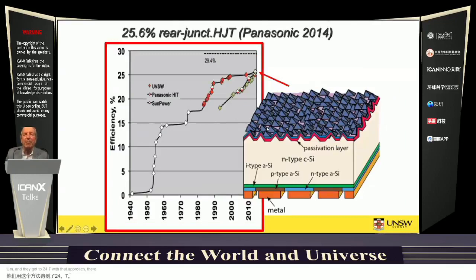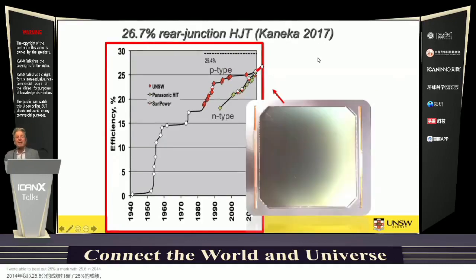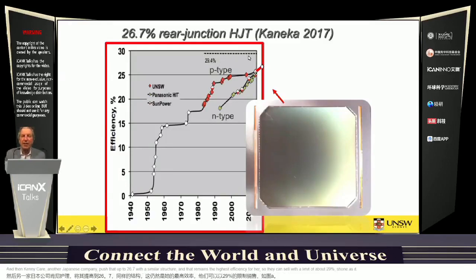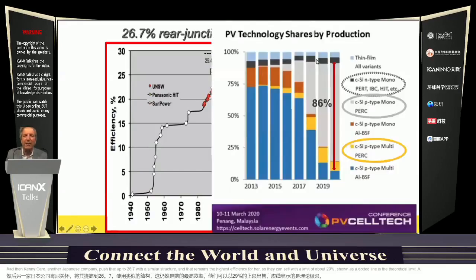And then by combining their approach with the Stanford University rear contact approach, we were able to beat our 25% mark with 25.6 in 2014. And then Kaneka, another Japanese company, pushed that up to 26.7 with a similar structure. And that remains the highest efficiency for a silicon cell, with a limit of about 29%, shown as the dotted line, which is the theoretical limit of how high you can go.